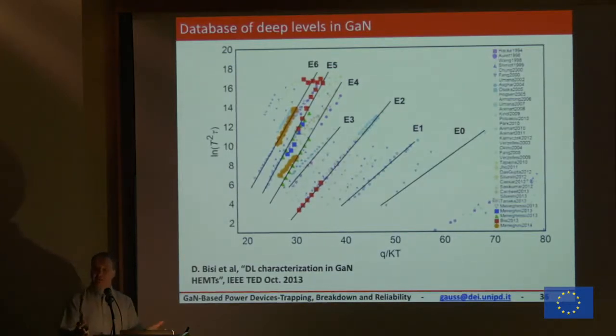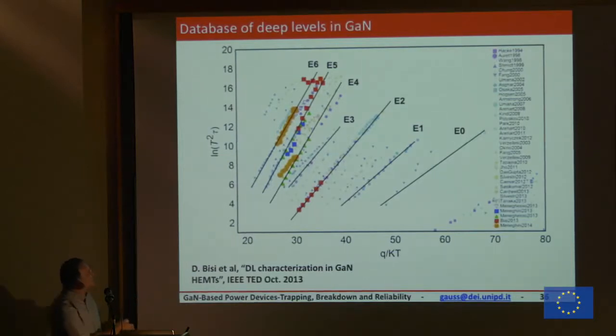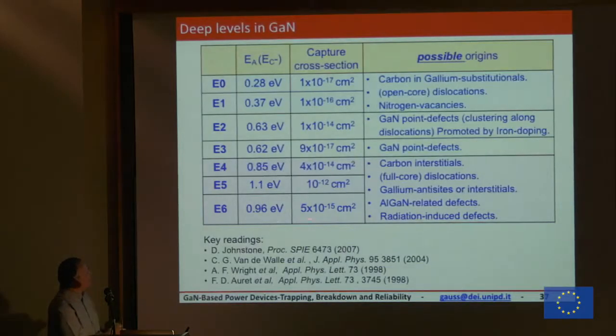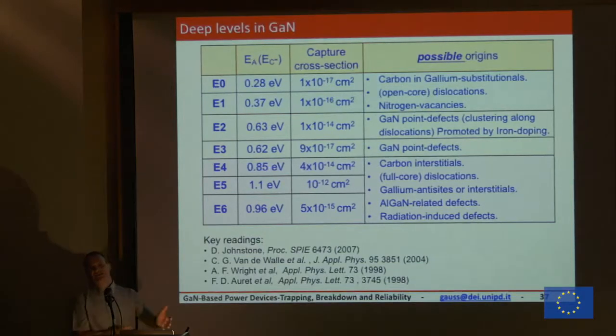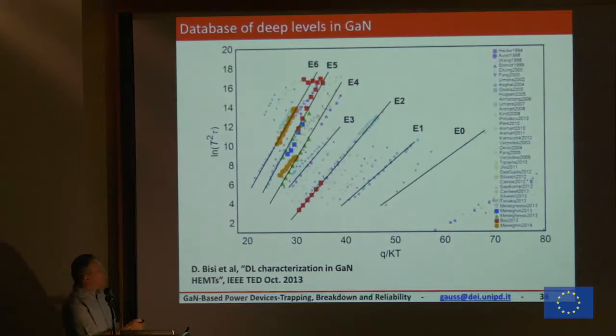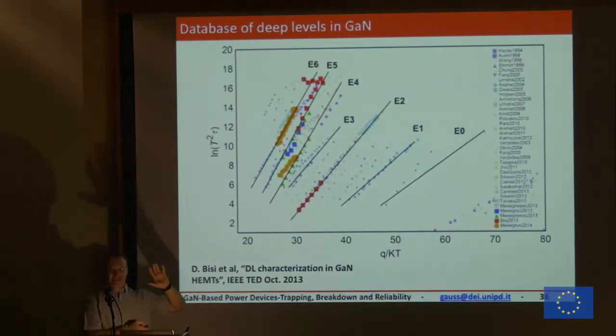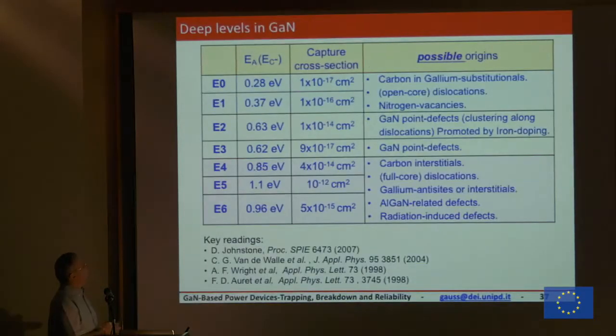Then what we do is kind of empirical, but very useful. We say, if my trap E6 is lying here, let's see in the literature what they attributed to traps lying in this light blue circle, and so on. Maybe we found that for E6, these traps are related to carbon interstitial, gallium antisite defects, and so on. So this has been our matching. We took our measurements, matched them in our database, and looking at the properties of these traps, characterized again at the bulk material level, we were able to determine the kind of traps we were probing.